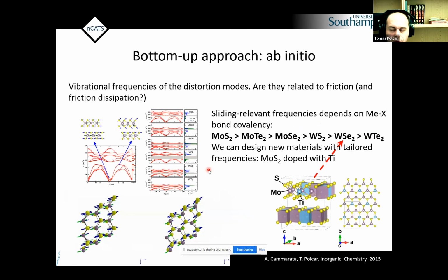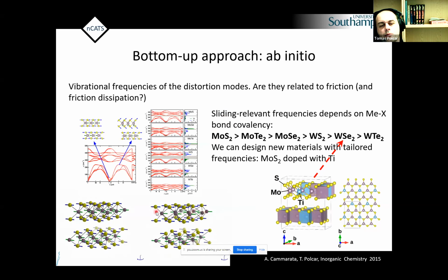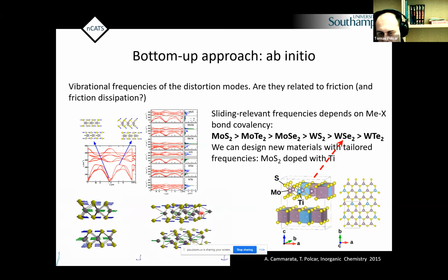Another one was developed by Antonio Cammarata, who is now as well in the audience. And he looked at vibrational frequencies of the distortion modes and tried to identify those which may be related to friction and friction dissipation, of course, because we speak about dissipation of energy. And what he did, basically, is he successfully identified those vibrational frequencies which may be related to friction. And then it allows him to look for perhaps even nanoscale design of new materials, because if there are some modes which influence the friction, either positively by decreasing or negatively by increasing the friction force, we can perhaps design the material to control them and produce a material with even lower friction than standard graphene or molybdenum disulfide, for example.